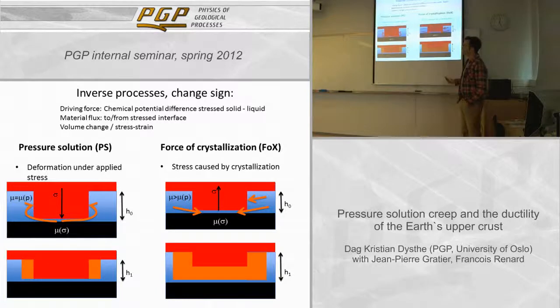And actually, it is possible to have the opposite process, which Anya has spent some time studying, where you start out with the fluid not being in equilibrium with the grains, but being supersaturated, so that you have a solution that has a much higher chemical potential, also higher than the chemical potential inside here. And then you will grow both inside and outside, and because of the larger chemical potential, you can set up a stress and actually push up and do work against the environment. So in this case, the environment is doing work on these grains. In this case, this grain boundary is doing work on the environment.